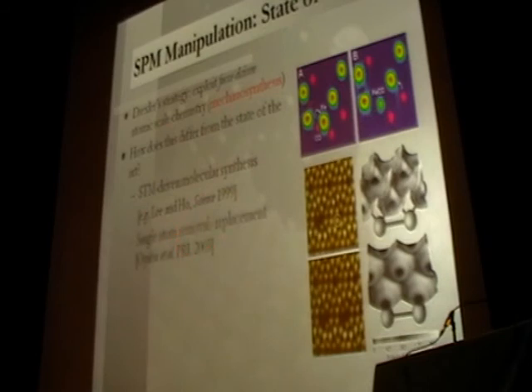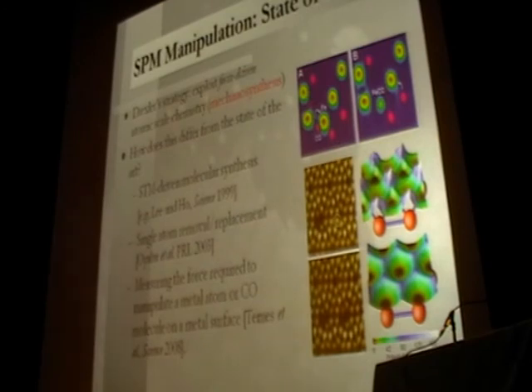So we've had STM-driven molecular systems synthesis, as I mentioned. We've had atomic force, so in this case we have another type of microscope which doesn't rely, scanning probe microscope, which doesn't rely on measuring a tunnel current, and therefore you can use it on insulators, where you actually measure the forces directly. If you're interested, I can tell you about that if you want to ask questions later. But the key thing is, with this atomic force microscope, single atom removal and replacement has actually been demonstrated. So if you compare these two images, this atom has been actually removed in the lower image. And most recently, a group has finally measured the force required to manipulate a single atom or a single CO molecule on a metal surface.